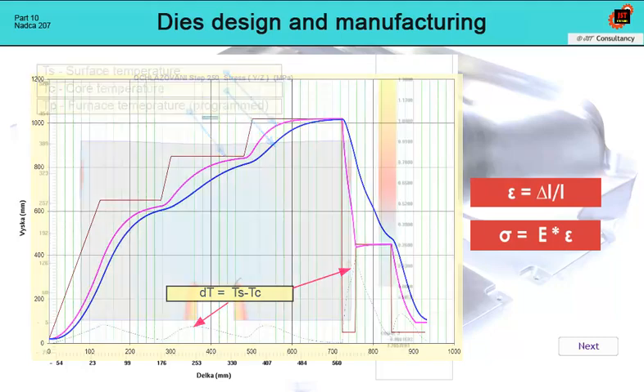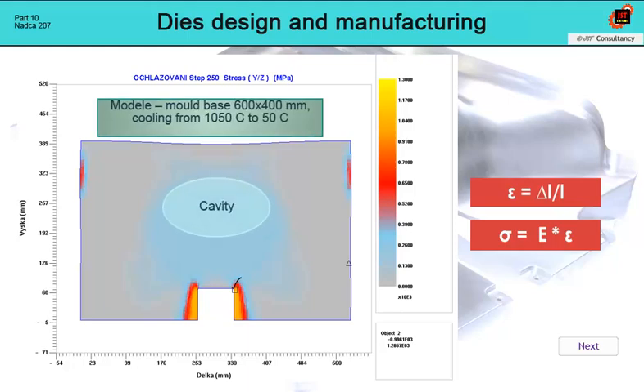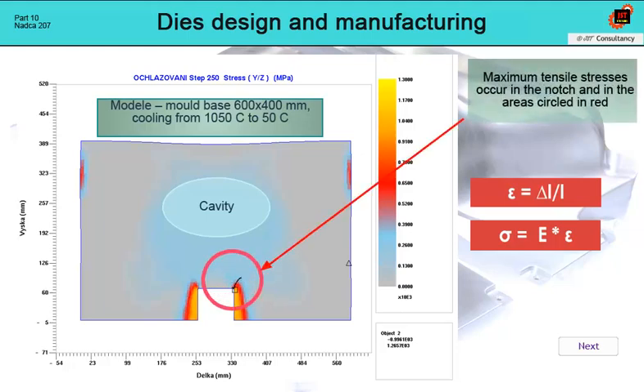The picture shows a model of a mold base measuring 600 by 400 millimeters, on which the state of stress was modeled during cooling from a temperature of 1050 to 50 degrees Celsius. Since the most dangerous source of cracks are tensile stresses, we focused on these stresses during the analysis. From the figure, it can be seen that the critical areas are around the notch, and at the same time there are other areas on the periphery of the mold base, lying outside the proper cavity.